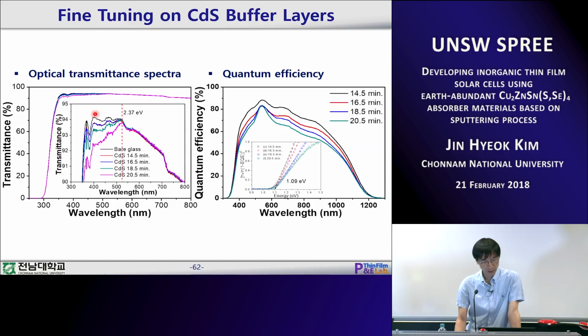And also in the long wavelengths, if we reduce the thickness of the buffer layer, we can reduce the oxygen or hydroxide, which is generally present in the buffer layer and is very harmful for long wavelengths. So if we decrease the thickness of the buffer layer, we could minimize the amount of oxygen and hydroxide. That means we can get much more long wavelength light into the absorber. That gives more photon generation and charge carriers. So I think that is the reason why we could have high cell efficiency with a very thin buffer layer.